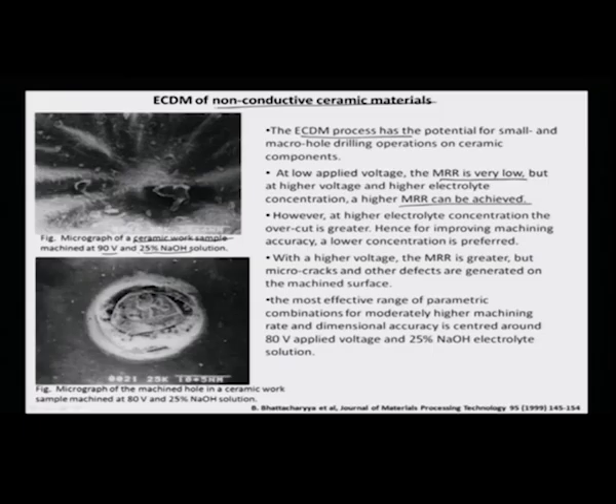And the thing which is important for me to tell here is that at a higher electrolyte concentration there is an increasing overcut in the machining, and the accuracy of the machined surface varies at a higher concentration. So typically people prefer either medium or lower concentrations of electrolytes in this ECDM case. This again is a micrograph of a machined hole in a ceramic work sample machined at 80 volts, 25% NaOH electrolyte.